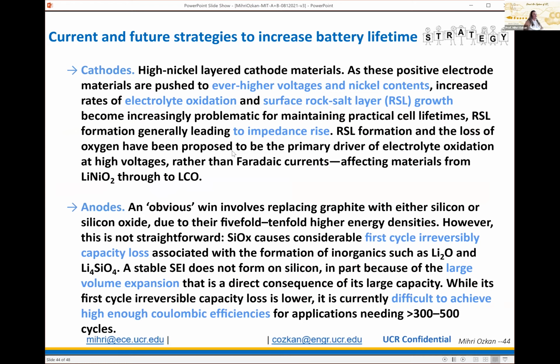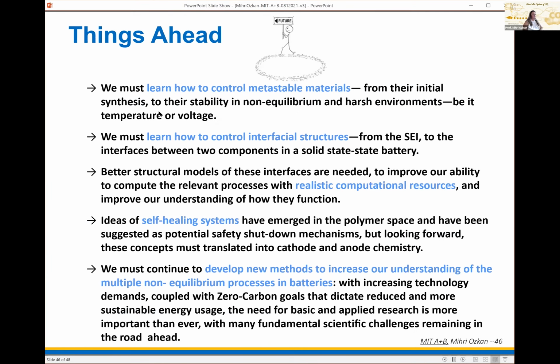Yeah, almost there. The current trend is higher voltages and higher nickel content, but it brings issues with electrolyte oxidation, surface rock salt layer growth, and high impedance. On the anode side, there are issues with irreversibility, first cycle capacity loss, and high volume expansion with the addition of silicon, and it is also difficult to achieve high enough Coulombic efficiencies at cycle numbers larger than 300. So we need to learn how to control metastable materials, learn how to control the interfacial structures, and have better computational resources. We still need to work on self-healing systems, and also try to better understand the multiple non-equilibrium processes in the battery.